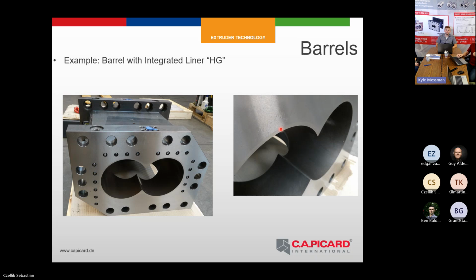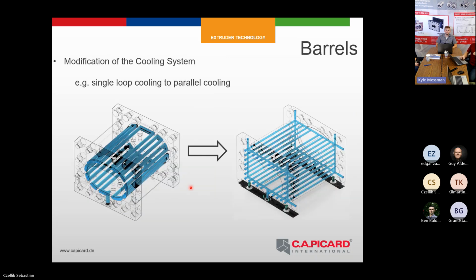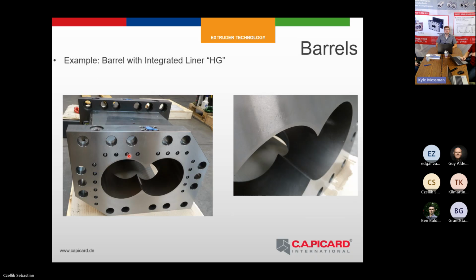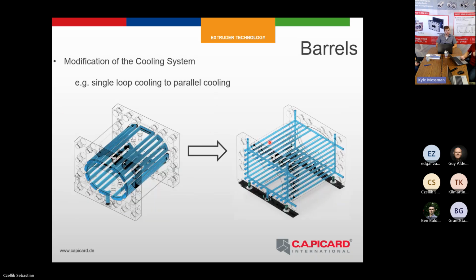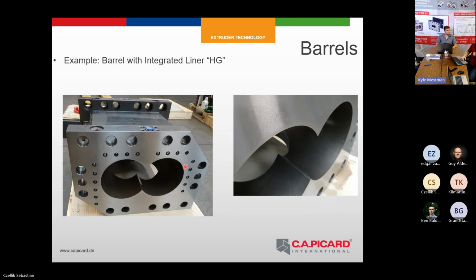There was another challenge, and that was the cooling system. The usual cooling system in these barrels is the single loop cooling system like here, but we could not do this in this case, because this cooling system is usually welded on the front side. The problem is that if we weld it here, we again have an influence of warpage because of the welding process, so we had a bad impact on our layer. So we had to modify the cooling system. We made this one, a parallel cooling, because we don't have to weld it. We can close this here with some expanders.